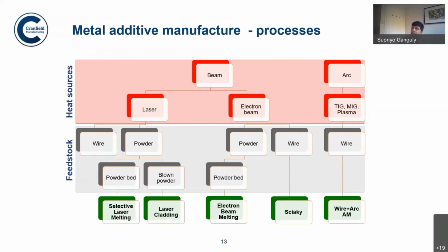So that is one of the disadvantages of MIG process to do very high-end job, but MIG can be quite good for other types of process. Particularly, we are using MIG and we use cold wire. So cold wire MIG basically to generate very large scale structures, and there the cold wire which is fed into the arc or into the weld pool is basically used to control the heat input, and the cold wire feeding can be controlled independently. So we are trying to bring GMAW process as it is quite easy to control, and the wire is the electrode, so wire feeding is central. There is no direction dependency and things like that, which makes it quite a nice process. With all these welding processes, we use wire, and that's why we call it wire plus arc additive manufacture.